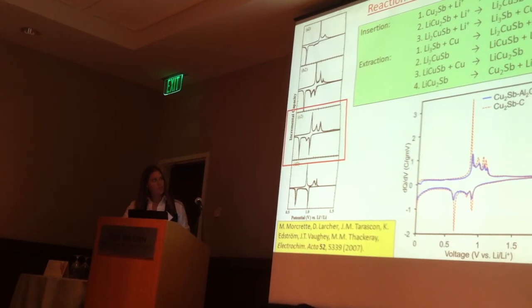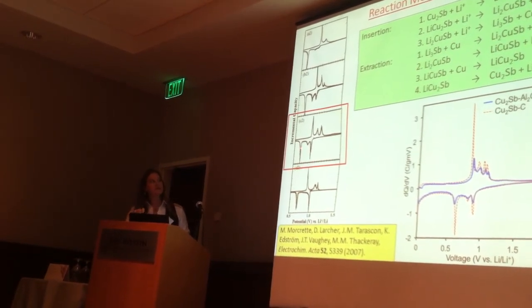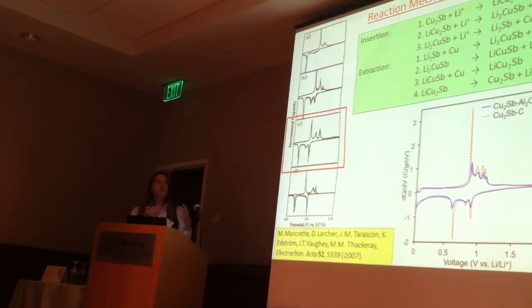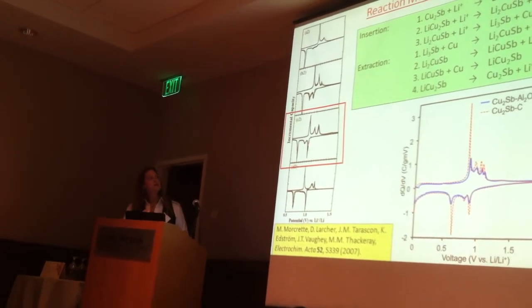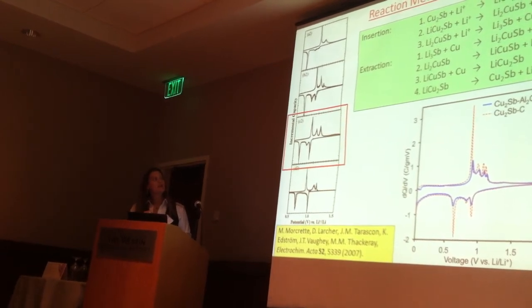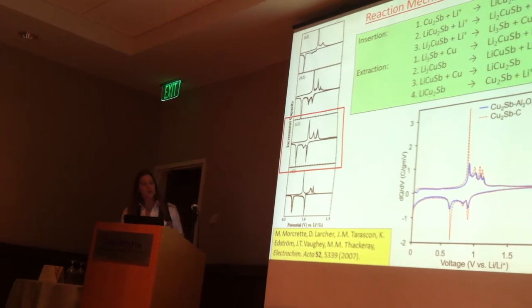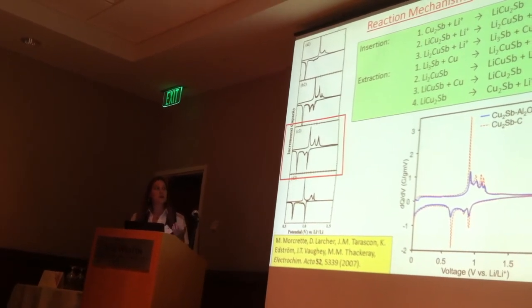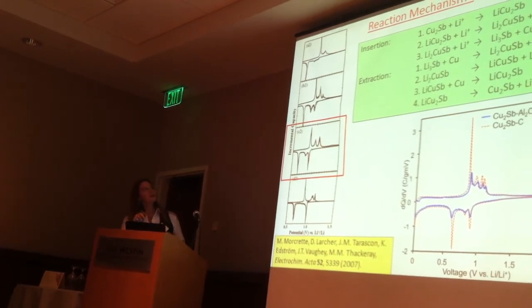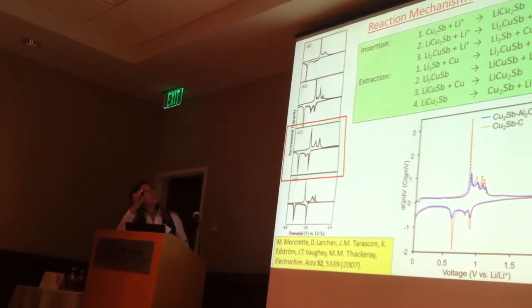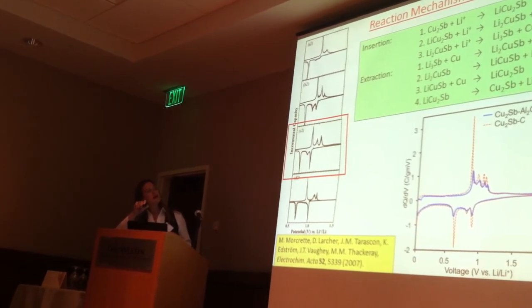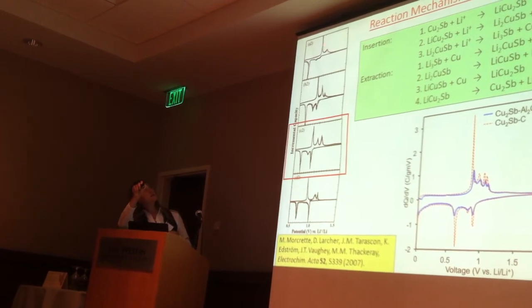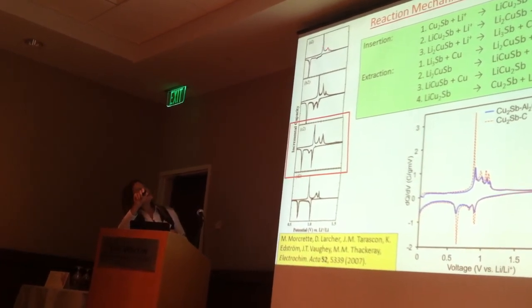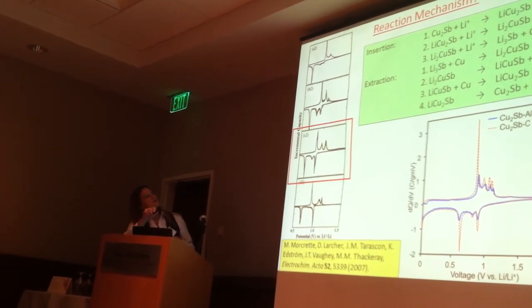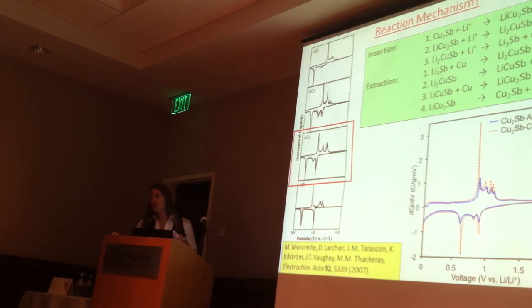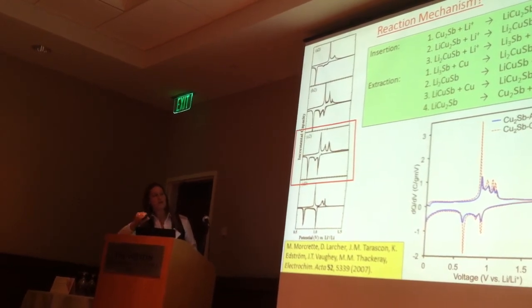But we know that when we look at the literature, this is published data for Cu2Sb that has been ball milled with carbon, and it's the most analogous to our materials. And we see 3 lithium insertion peaks, 3 lithium extraction peaks. Our material is different in a few ways, and one of the ways is the particle size. So also, if you compare, I just looked this up this morning, this is the same as this material. However, this has been ball milled, and it's about 30 nanometers in size. This one is about 200 nanometers in size, and you can see in the insertion part, there's only 2 peaks here. There's 3 peaks here, and when you go even smaller to our particles, which are 2 to 20 nanometers in range, you see 4 peaks.